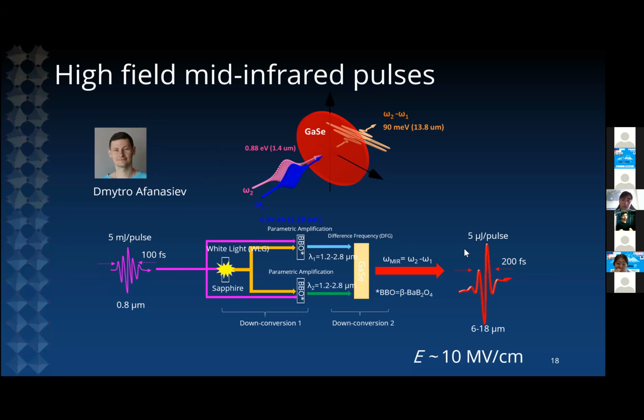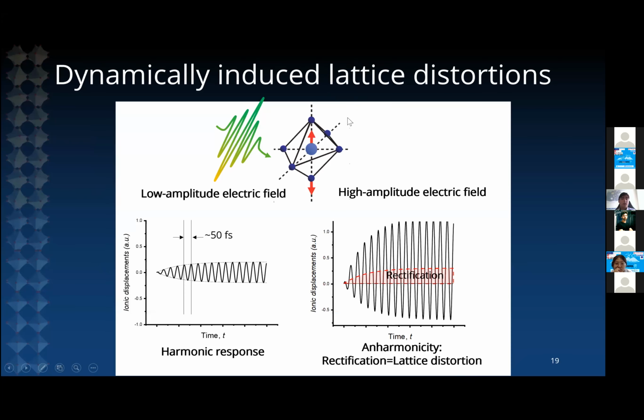So it's a relatively inefficient process, but still the laser pulses that we obtain at the end are of the order of 10 megavolt per centimeter in terms of electric fields. So a significant fraction of the electric fields that we find in matter. So we can expect to significantly perturb the atomic positions. So our objective is to dynamically induce lattice distortions in the material.